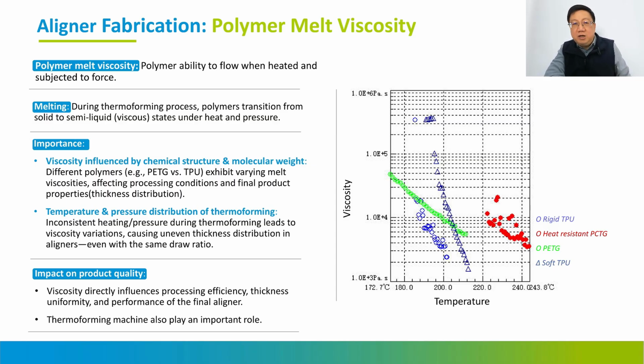So this really relates to how you make the aligner, because when you heat the material and do the fabrication, the problem is that there is pressure, there is temperature, and it's a cooling down process. If the viscosity changes too fast, the thickness distribution will become more varied and bigger. But if the viscosity does not change a lot, the thickness distribution around the aligner will be more stable. So this is very important.